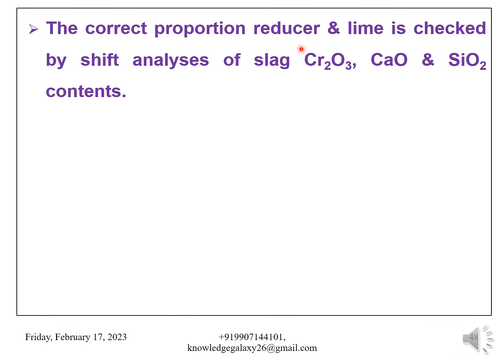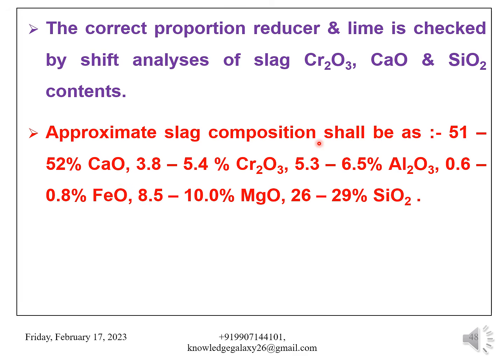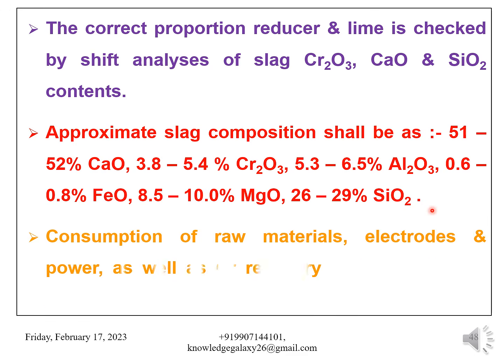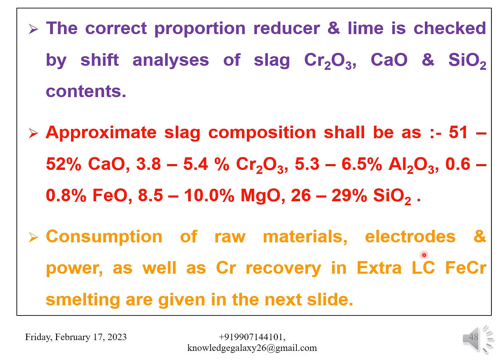The correct proportion of reducer and lime is checked by shift analysis of slag for Cr2O3, CaO and SiO2 contents. The approximate slag composition shall be 51 to 52% CaO, 3.8 to 5.4% Cr2O3, 5.3 to 6.5% Al2O3, 0.6 to 0.8% FeO, 8.5 to 10% MgO, and 26 to 29% SiO2. Consumptions of raw materials, electrodes and power, as well as chromium recovery in extra low carbon ferrochrome smelting, are given in the next slide.